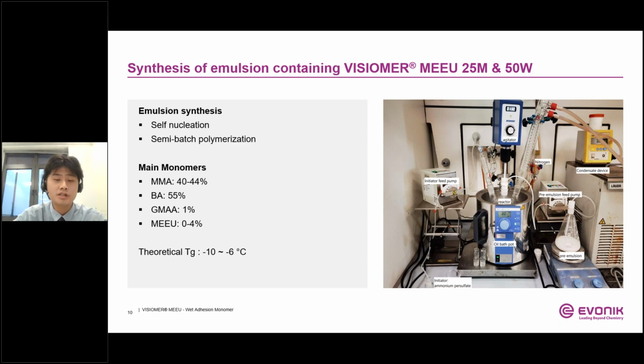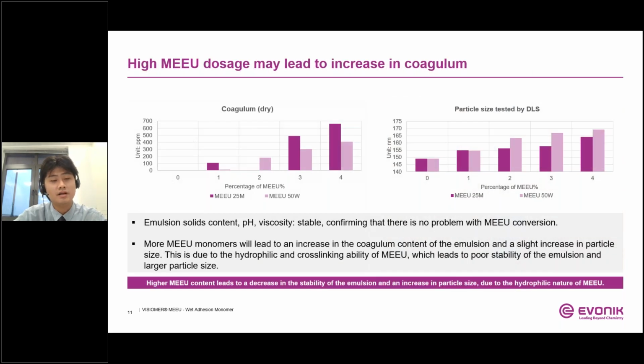To facilitate film formation at room temperature, we designed the glass transition temperature of the whole film to be about -10 to -6 degrees. And you can see the right-hand side picture is our reaction device. Here comes the performance characteristics of the emulsion. It can be confirmed that there is no problem with the conversion of MEEU monomer because the solid content, viscosity, and pH are quite stable.